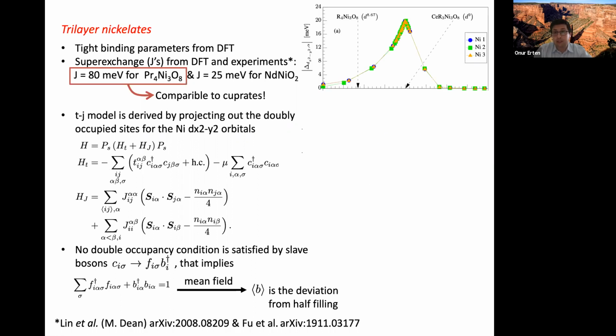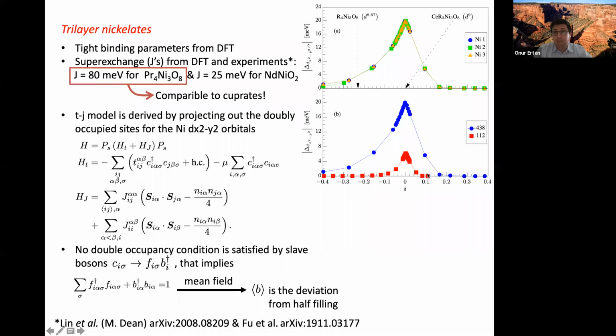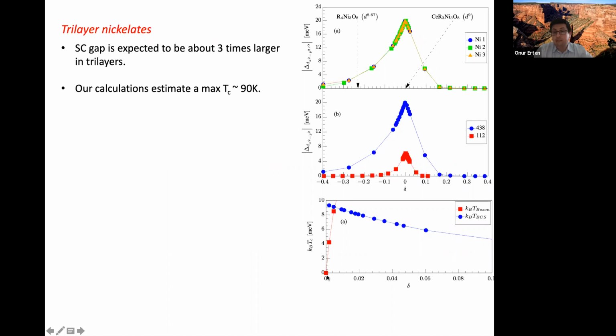So what we find is that the superconducting gap is much larger in the tri-layer compared to 112s, both because the super exchange is large, and also the fact that there's no rare earth band here also enhances superconductivity. And we estimate the TC near half filling. The TC is set by the boson condensation of the slave bosons, and at high doping, it's the BCS condensation. And the real TC is determined by which one is the lower, so this gives you roughly a dome. And our calculations estimate a maximum TC of about 90 Kelvin.